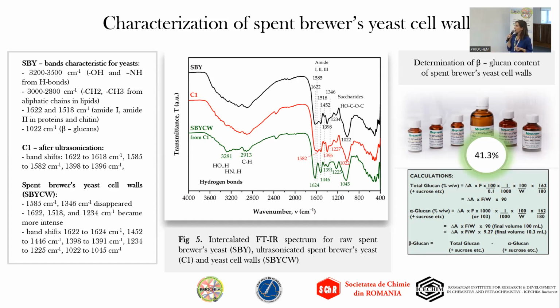Also, the beta-glucan content of the yeast cell walls was determined using the Megazyme yeast and mushroom beta-glucan determination kit. After performing the steps provided by the kit, the results showed 41.3% of beta-glucan, which, according to the present literature, is a pretty standard content of beta-glucan. So it confirms once again that we indeed obtained yeast cell walls.